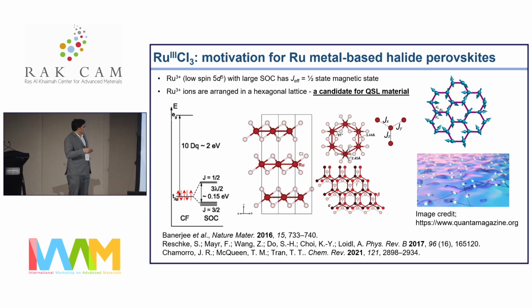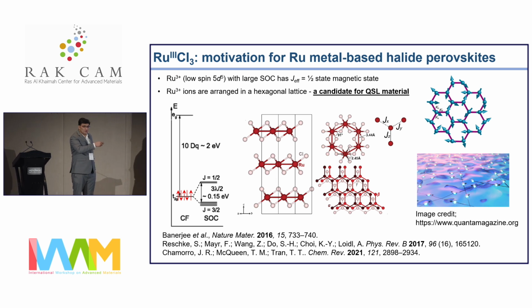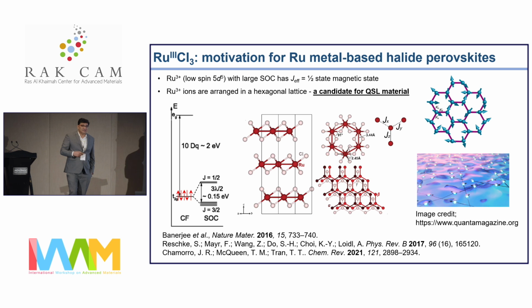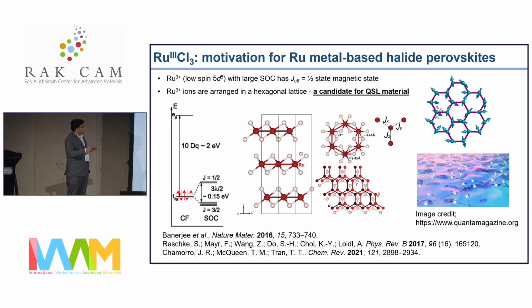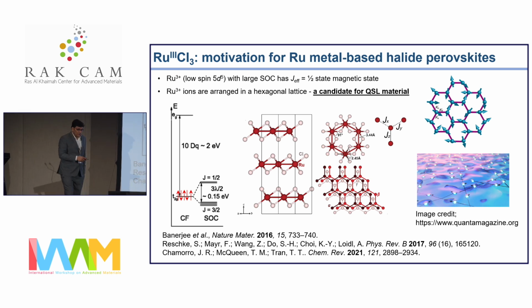And here is the electronic configuration. Ruthenium has t2g and eg orbitals in an octahedral setting, which are split because of the six chloride ligands around, and ruthenium is always, no matter what the ligand is, going to be low spin because of the heavy metal. We have one unpaired spin, which further splits because of SOC, and we have a J effective half system. When these atoms are in the hexagonal setting, this kind of magnetic correlation is expected, which is basically the quantum spin liquid behavior.